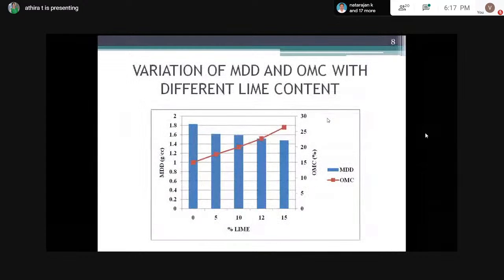First of all, different lime contents were taken and compaction test was conducted to determine the variation of maximum dry density as well as optimum moisture content. From the graph we can see that as the percentage of the lime increases, the maximum dry density is found to be decreasing, whereas the optimum moisture content shows an increasing trend.